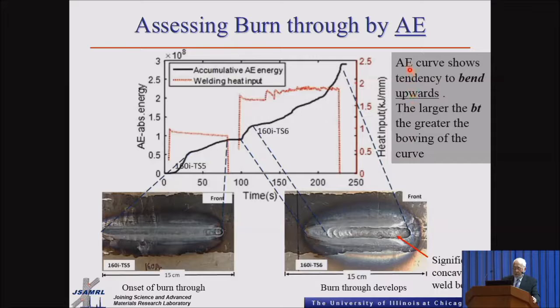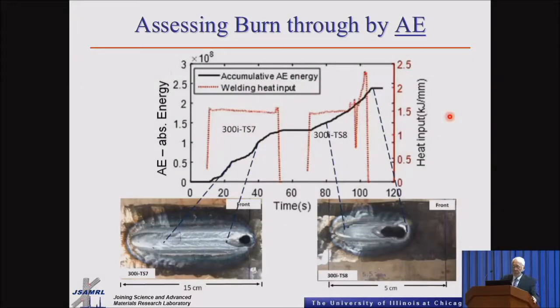So based on this analysis, we see that the acoustic emission curve shows this tendency, and that is telling us that you have some possible burn through. When it comes to the case of the real burn through, in which you have the hole, you can see this curvature increasing even much greater. This one in here, you might say, well, you don't have too much of a curvature. Well, the reason is the weld was very short because we immediately got a hole, so you got a burn through. Okay, so that was with acoustic emission.